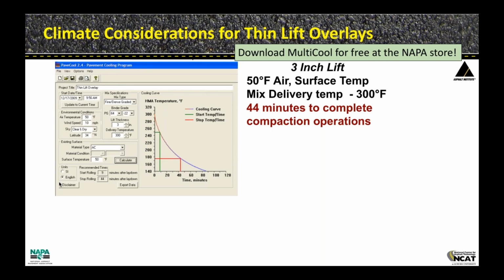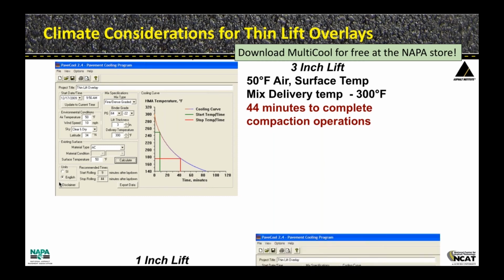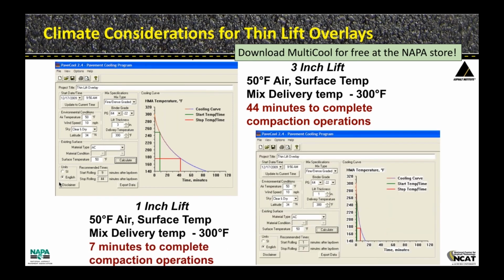So for this example, under these conditions, placed at 3 inches, we've got 44 minutes to achieve compaction. However, if you consider placing a 1-inch lift and have everything remain the same, air temperature, surface temperature, mix delivery temperature, everything else remaining the same, to get to that 175, you now only have 7 minutes.